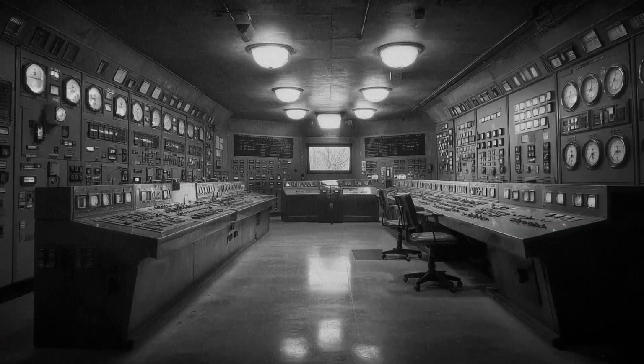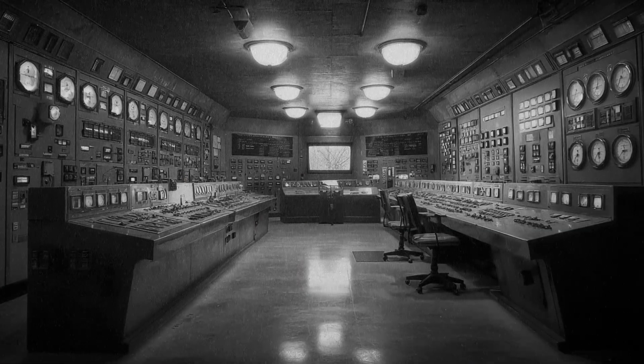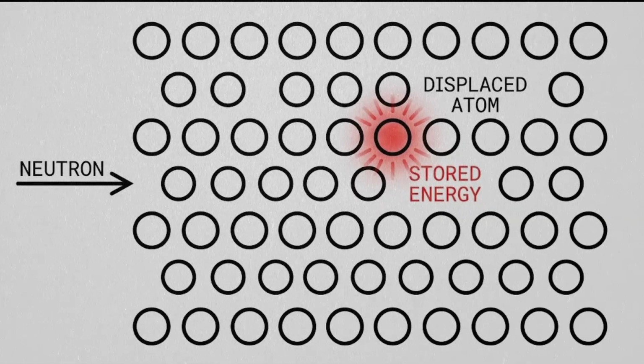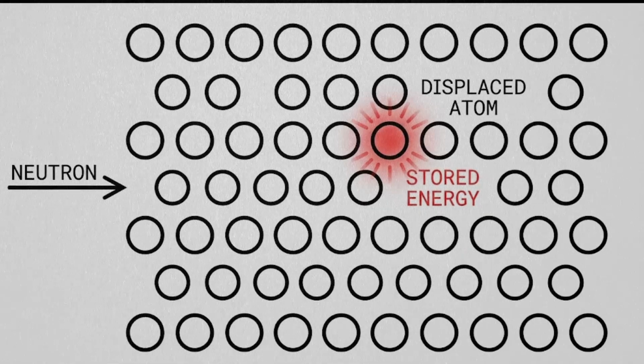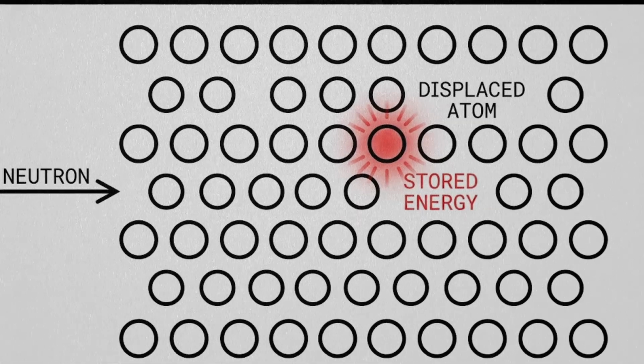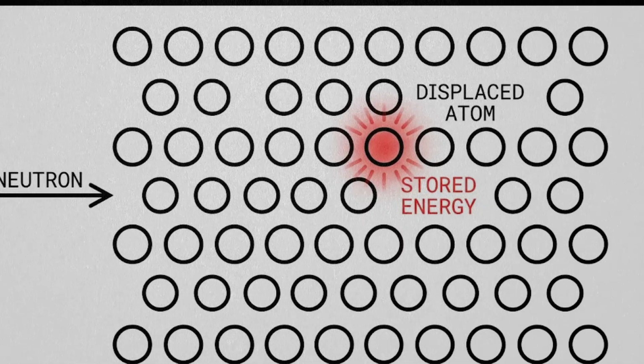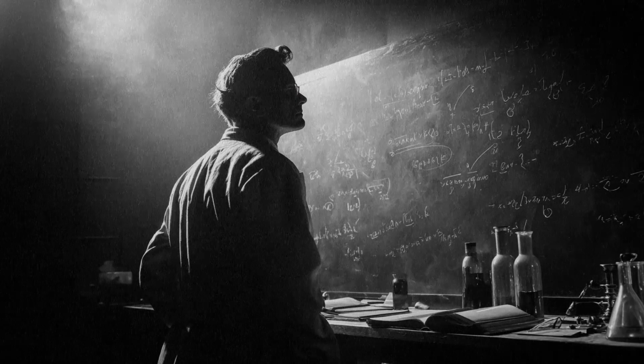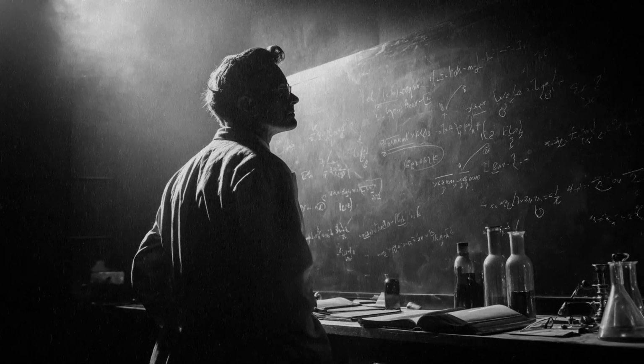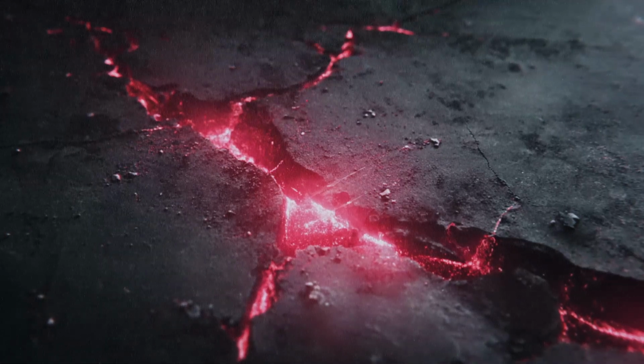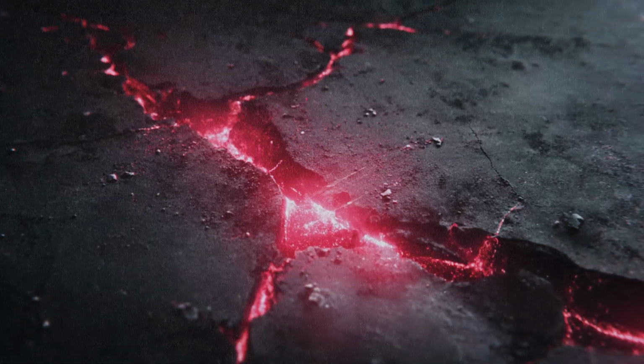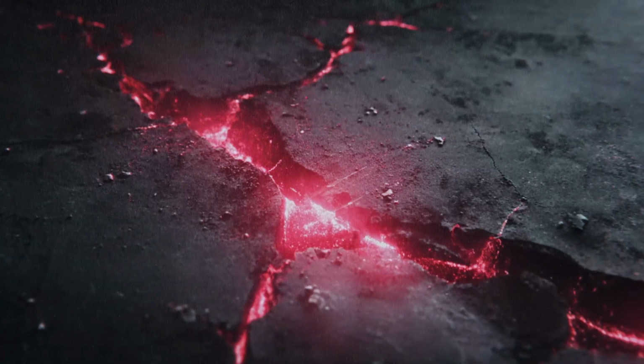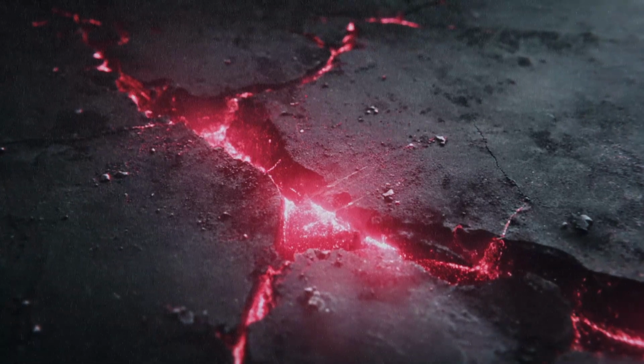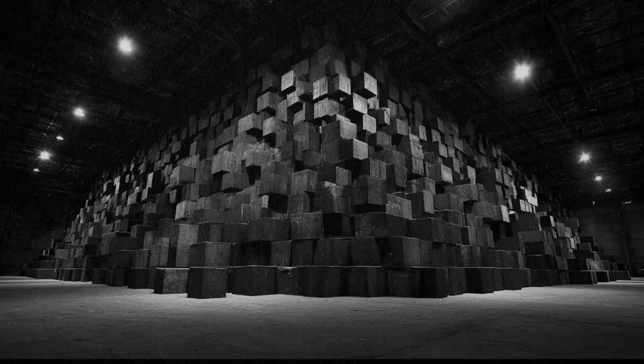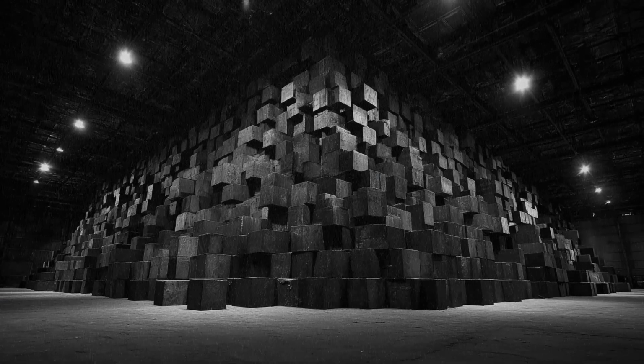By 1957, the reactor had been running for 40,000 megawatt hours. And the graphite had a problem. When neutrons strike carbon atoms in a graphite lattice, they knock them out of position, creating microscopic defects that store energy. Physicists called this Wigner energy, after the Nobel laureate who predicted it. Left unchecked, it accumulates, up to 2,000 joules per gram. Enough to heat the graphite by several hundred degrees in an instant, without any external source of fire. 2,000 tons of it, all storing that energy.